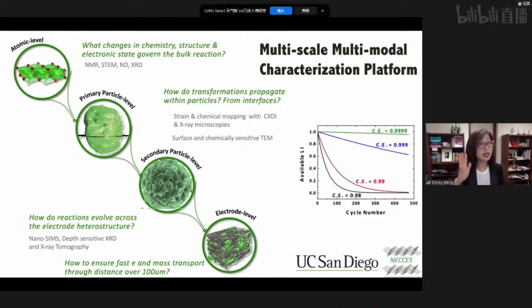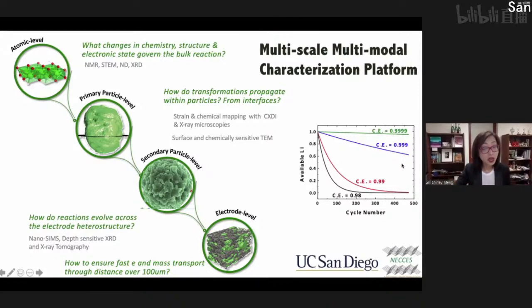Because if you have any inefficiency that causes the loss of lithium, even 1%, it can cause a very detrimental effect on your battery's cycle life. And this graph very simply shows the importance of Coulombic efficiencies. When we have a battery that can last for 1,000 cycles, the lithium shuttling between the cathode and anode is highly efficient. So if we are building characterization techniques and trying to decipher where the degradation happens, this job is very difficult because the change is indeed very, very subtle. We're trying to detect less than 0.1% of the degradation phenomena.